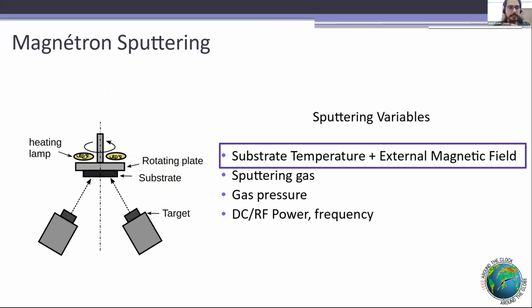In this particular work, we are focused on magnetron sputtering, where it's widely applied and has great interest to upscale the production of thin films. Of the several variables that are available in the sputtering system, we are interested in applying external magnetic fields with substrate temperature, to understand how magnetic fields in different directions, when applied during the sputtering deposition, can influence magnetic and structural properties, while all the other variables are kept the same.